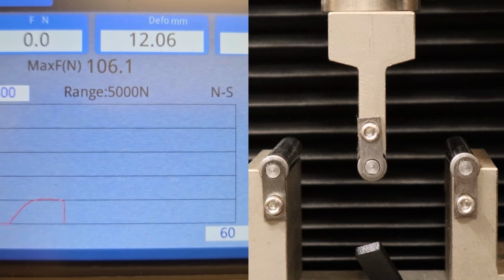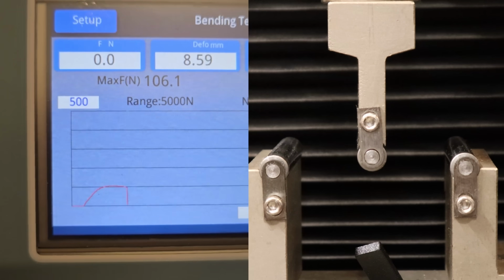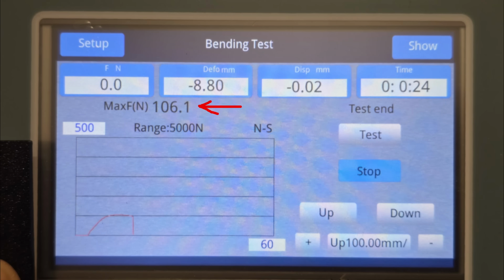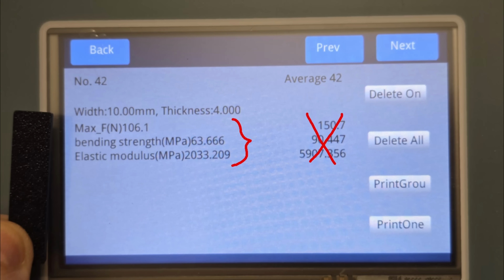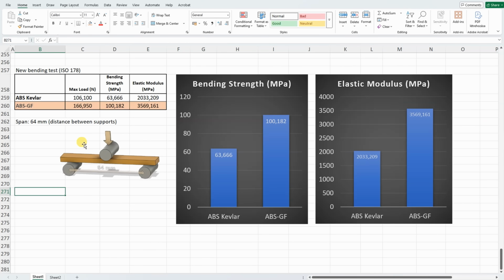And you can see the maximal load is 106.1 newtons, and you can see the graph here. And here you can see the bending strength and elastic modulus. This is a new test and I don't have enough data, so I have only here ABS GF, which is the closest. And here we can see that the ABS GF has much better bending strength and even elastic modulus.